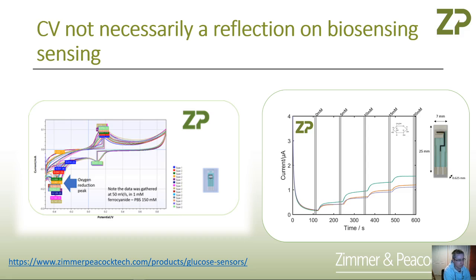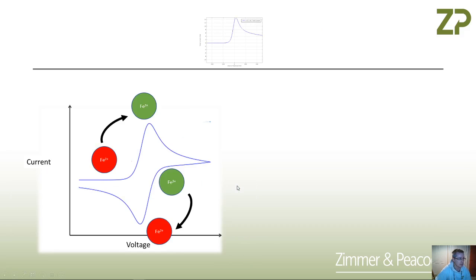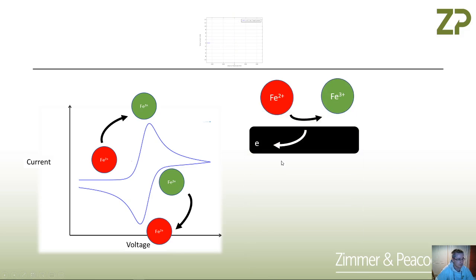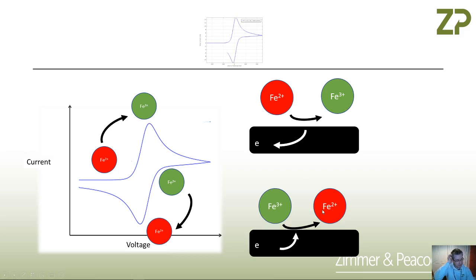The real-world example shows that cyclic voltammetry is interesting, but you don't need a perfect peak separation of 59 millivolts or peak-to-peak height ratio of 1 for it to go on to be a perfectly good biosensor. In our cyclic voltammetry, we're oxidizing ferrocyanide to ferricyanide on the oxidation wave, and then reducing ferricyanide back to ferrocyanide on the reduction. It's quite a simple system — you've just got an electrode in contact with a redox-active molecule.